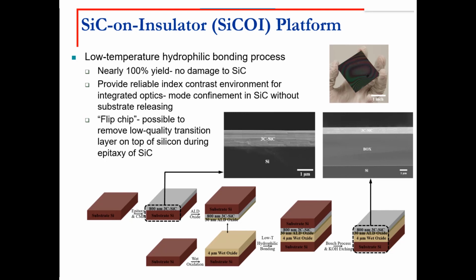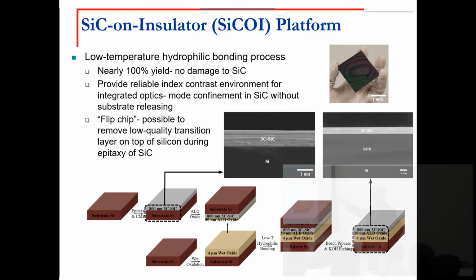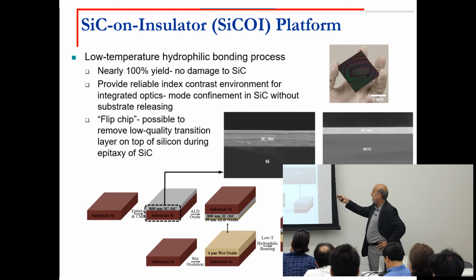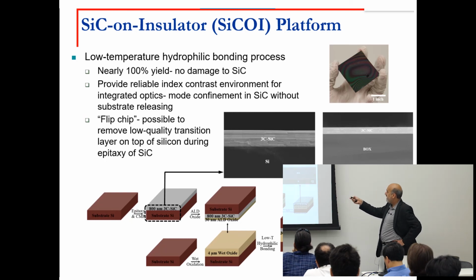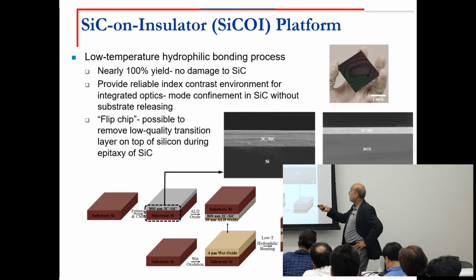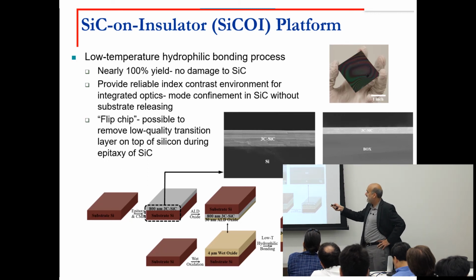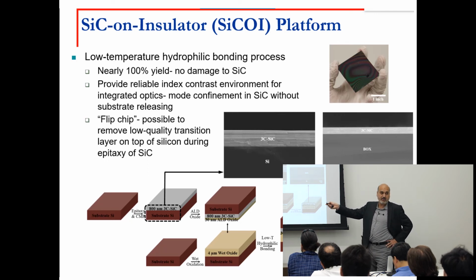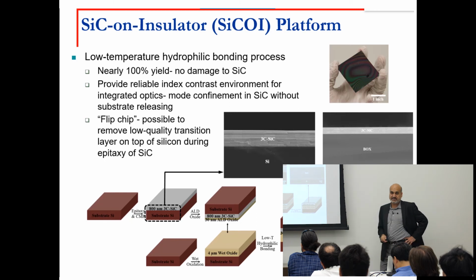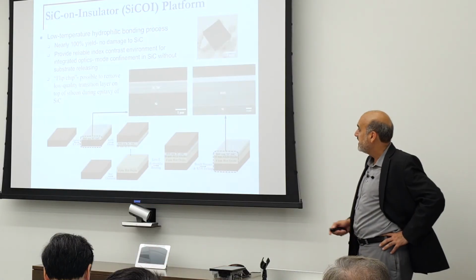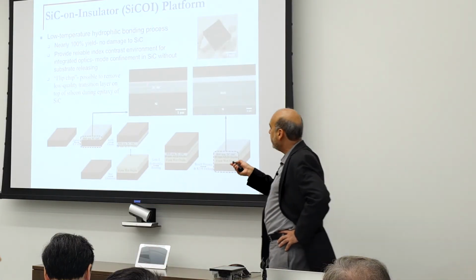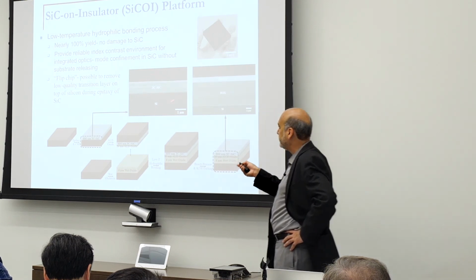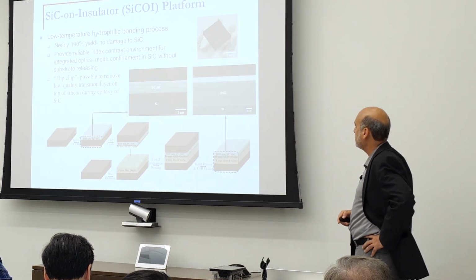Now, typically, when you grow silicon carbide on silicon, the problem that you face is that the bottom surface of carbide has a lot of defects and problems in it because of the mismatch that exists between the two materials. So that has hindered the integrated photonic devices that utilize silicon carbide.